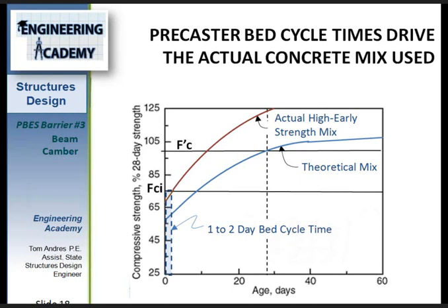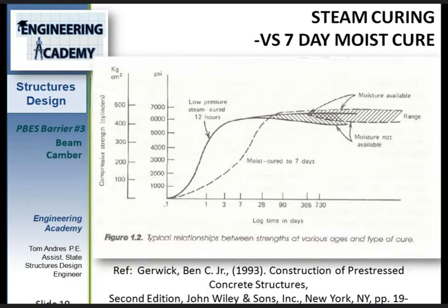As you know, programs apply correction factors to approximate the real strength gain curve when predicting cambers. Interestingly, when we switched from the Florida bulb tees and AASHTO beam shapes to the new Florida I-beams, the actual cambers were about half of the predicted values. This, of course, is because these new beams are inherently more efficient, and it is the stiffness term, the EI term, that has to be accounted for in the correction factor, not simply the E term. So the correction factor for the old beam shapes doesn't really work on the newer beams. Just an interesting scenario here.